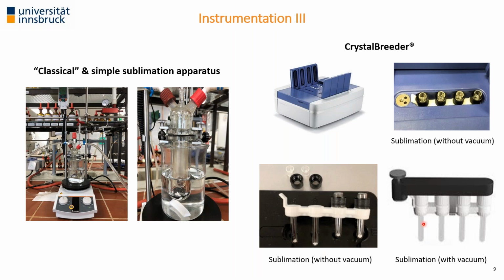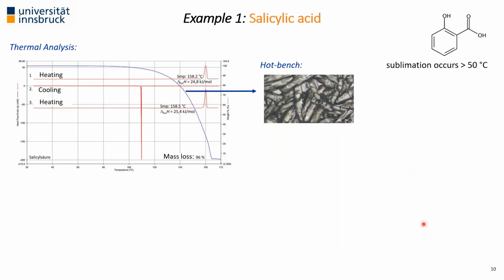And within the scope of a diploma thesis, we tried several examples, and a few of them I'm now sharing with you. The first one was salicylic acid. Why have we chosen this compound? Because from literature, it is known to sublime heavily, and sublimation occurs at temperatures slightly above 50 centigrade. We complemented our sublimation experiment with thermal analysis. So the blue curve here gives you the TGA curve. What we have done is take the compound, heat it up under controlled conditions, and do weighing operations. And so we see the mass loss corresponds to the sublimation.